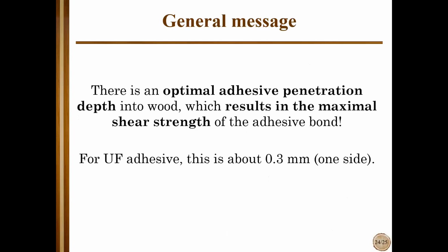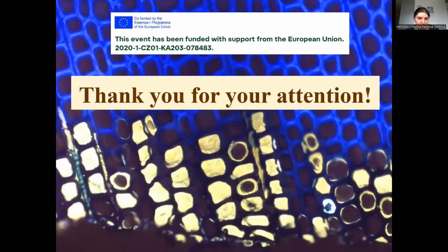And the main message from this research is that there is an optimal adhesive penetration depth into wood, which results in the maximal shear strength of the adhesive bond. And in the case of the investigated urea-formaldehyde adhesive, this was about 0.3 millimeters on one side. So altogether it would be a bit more than 0.5 millimeter. And with this, I thank you for your attention.